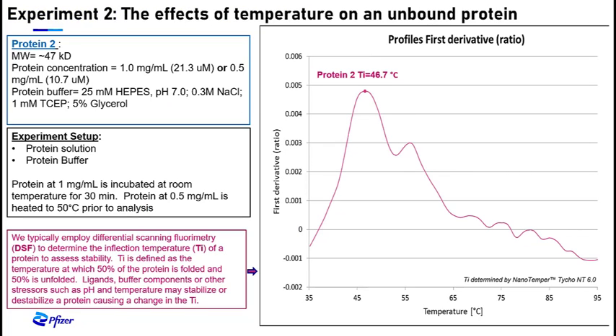In our next experiment, we'll look at a different protein, which is about 47,000 Daltons. Here we're going to look at the effect of temperature on this protein. We've prepared the protein at 1 mg per ml and 0.5 mg per ml. We've incubated the 1 mg per ml sample for 30 minutes at room temperature, and we've taken the half mg per ml sample and incubated that at 50 degrees centigrade for 30 minutes. And again, our goal here was to observe what happens to the protein upon heating.